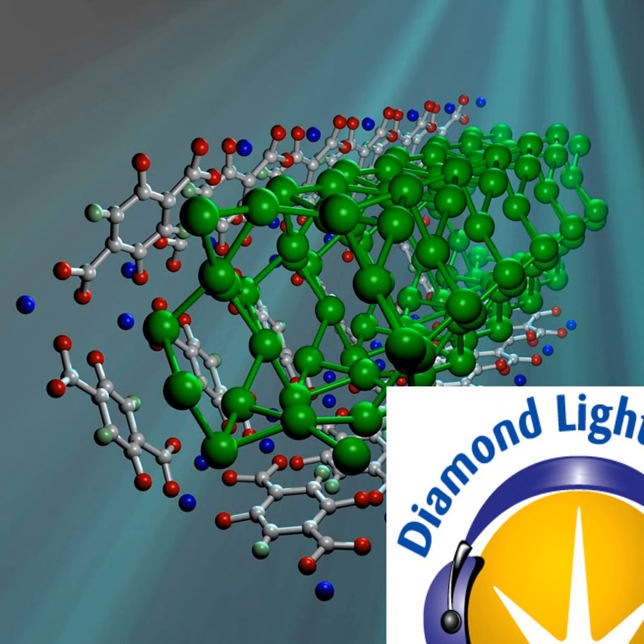So how are you taking this on with your catalyst? What is your catalyst and how does it work to bring these conditions down and produce methanol? Initially, the material we put in is small palladium metal particles, roughly 1 nanometer, 1 times 10 to the minus 9 of a meter, sitting on high surface area iron oxide. After reduction and during the reaction, some of the iron will be reduced from iron 3+ all the way down to iron 0, and then form a bimetallic species with the palladium. We believe this is the active phase, and from the XAFS evidence, it suggests the more palladium-iron species coming out, the better the activity.